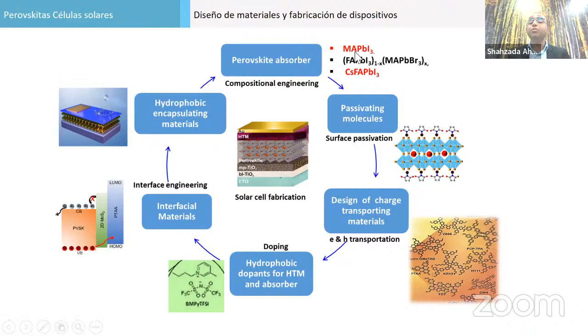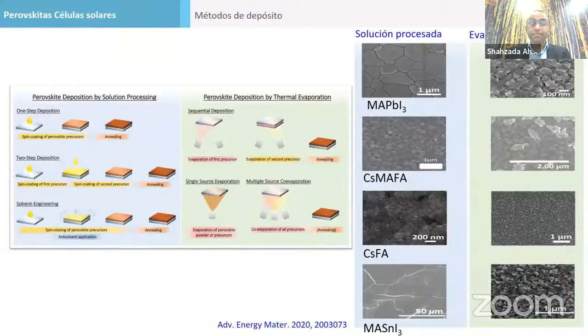What my lab is doing is working on the full value chain in a holistic manner. We develop different types of compositional engineering of perovskite, and the perovskite crystals are very large and sometimes have defects. They're very polar, so we passivate them with molecules to create a very good interface. We develop different types of P type and N type, what we call electron and hole transport materials. We develop different doping strategies, interfacial materials, hydrophobic doping.